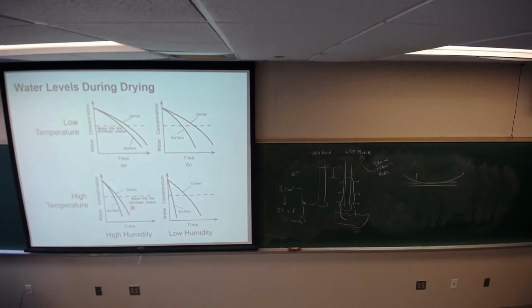If I'm at low temperature and low humidity, then look at the water content, draw a line here at a given time. We have a very narrow difference in moisture content from interior to exterior, and it says below this line shrinkage ceases. You have very little shrinkage necessary still in the system, whereas here, in this one in particular, you have a huge difference, and that leads to differential stresses. This is all predicated on the idea, though, that you can create cracking in drying.